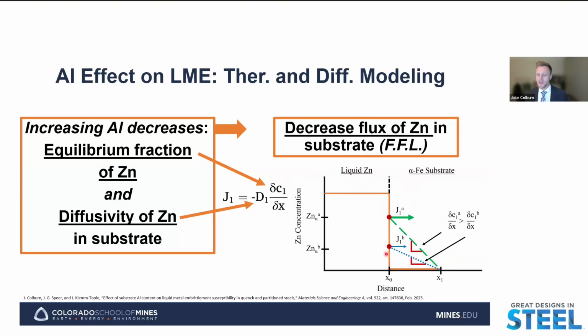And so here at the interface, we're showing that if we're changing the maximum solubility, if we're changing the equilibrium concentration of zinc in the substrate by adding aluminum, we're going to be changing the concentration gradient into the substrate. So we see that moving from a low aluminum concentration here in point A to a high aluminum concentration in the substrate in point B is going to, again, decrease the equilibrium fraction of zinc, the maximum solubility of zinc in the substrate, such that as we then move a distance into the substrate where there is no zinc, that concentration gradient is going to be decreased.